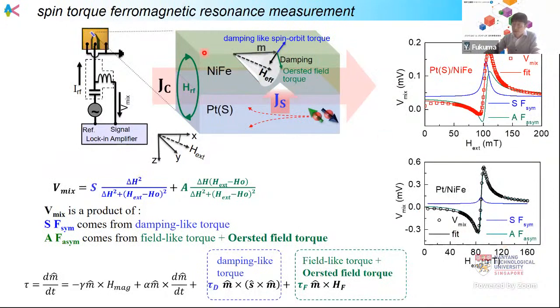Then we deposit permalloy on the sulfur-implanted platinum. For the characterization of the spin Hall effect, we use spin torque ferromagnetic resonance measurement. In this measurement, we apply a microwave current into the platinum layer. This current generates, of course, an electric field, and also generates a spin current as well. When we apply the microwave current into the sample, we can see this kind of rectifying voltage.